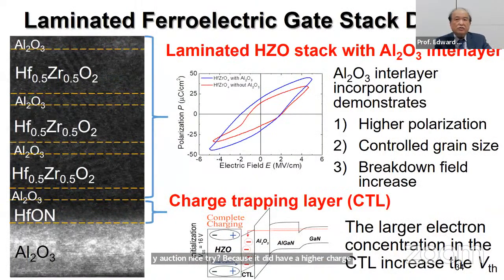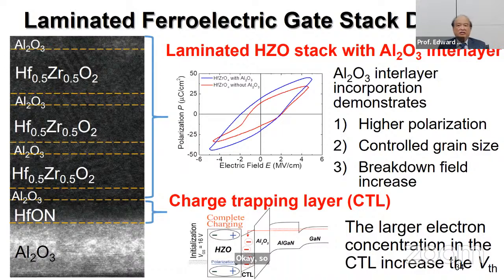So this is actually the laminated ferroelectric gate stack, laminated with aluminum oxide interlayers. In this kind of superlattice, because of the insertion of the aluminum oxide interlayer, it has high polarization, and the grain size, just like I said, can be controlled to a larger size. And then the breakdown field can be increased because the aluminum oxide can reduce the leakage current.